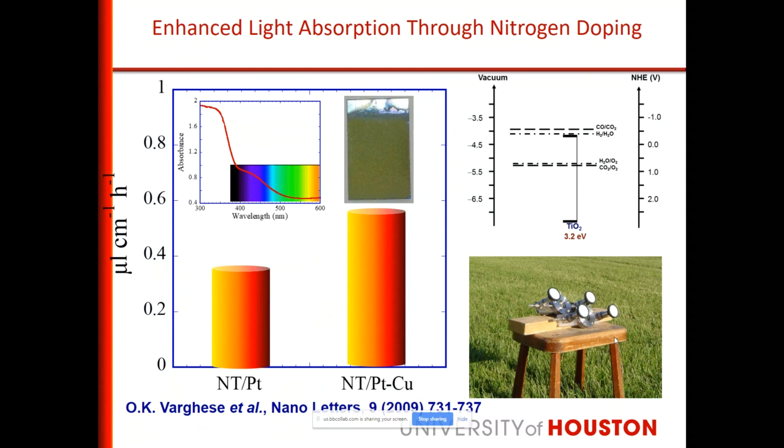So this we utilized for converting carbon dioxide and water vapor to methane. This is the chamber we used. We shine light, we fill the chamber with carbon dioxide and water vapor, keep a titanium dioxide film there, and then the carbon dioxide reacts with the water vapor and generates methane, or even other alkanes.